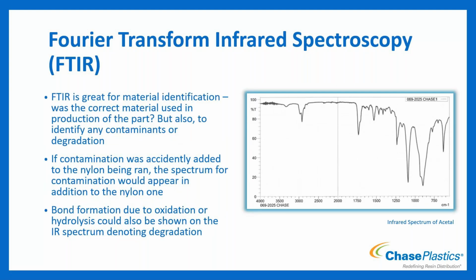Okay, so again, great for did we use the correct material? So if you've got a part that's breaking, you've got material that's clogging a gate, you've got material that appears to be contamination within a bag or box of material, FTIR can be used to determine what it is. So if you purchased nylon 6 and they do an FTIR curve and you're showing the spectrum of acetal, well, that's your contamination. Somehow some acetal material got in with your nylon, and that is a problem. And with other parts too, not just the material being a contaminant, but others as well. So contamination accidentally ending up in there, we would be able to tell that.